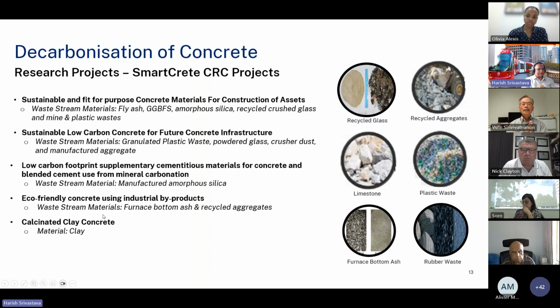Then the other important thing is using, say, bottom ash. We use fly ash a lot, but bottom ash is probably another potential material that can be used both as aggregate as well as SCM. And then we are also trying to develop some new streams of SCMs, for example, this manufactured amorphous silica. This is an interesting project because it comes out of the carbon dioxide injection process. So the overall process is intending to absorb and store the carbon dioxide, and the byproduct is amorphous silica, which we are trying to use in concrete both as SCM as well as aggregate.